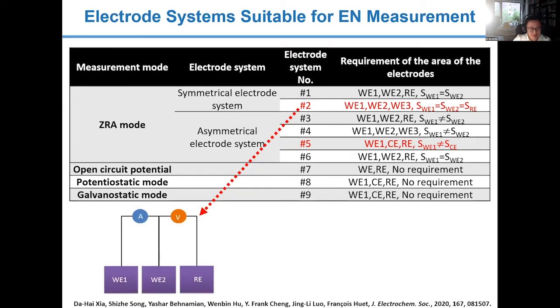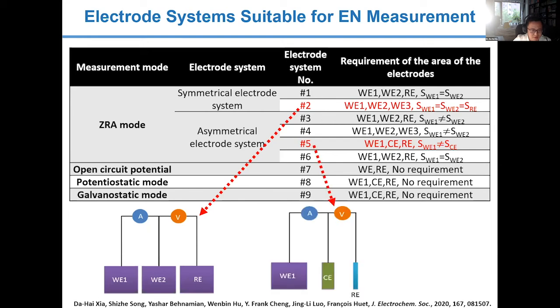In the ZRA mode, the electrode can be symmetrical or asymmetrical. Symmetrical electrodes incorporate 2 or 3 nominally identical working electrodes with the same surface area. And asymmetrical electrodes include a working electrode of the same material but different surface areas, and system with different materials in each of the working electrodes, the counter electrode and the reference electrode. So in this work, we used these 2 electrode systems, number 2 and number 5.